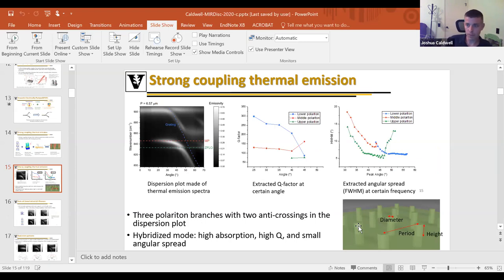However, in silicon carbide, especially with 4H silicon carbide, you fabricate these structures into the silicon carbide substrate itself. So this isn't silicon carbide pillars on, say, glass. This is silicon carbide pillars on silicon carbide. And as such, what you actually find is that that modifies the mode and couples into a propagating mode. So you have a localized propagating character that gives a monopole resonance. If you think of a monopole RF antenna, this is a dipole antenna on a metallic ground plane. It's the same concept, except my metal is an optical metal at these frequencies.